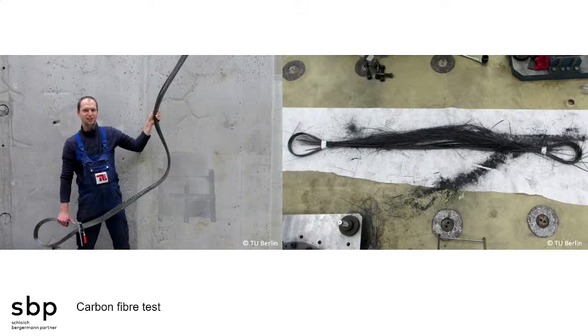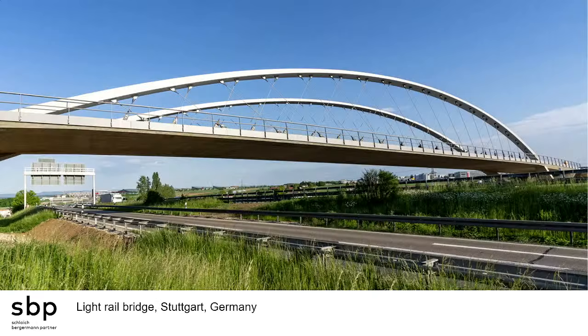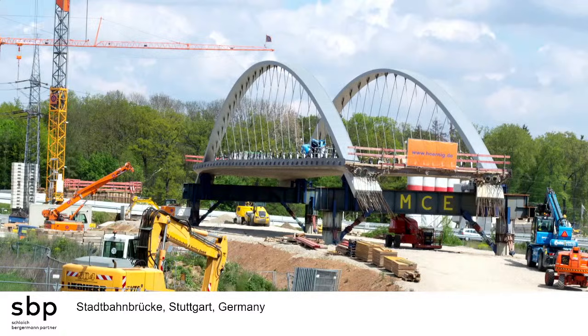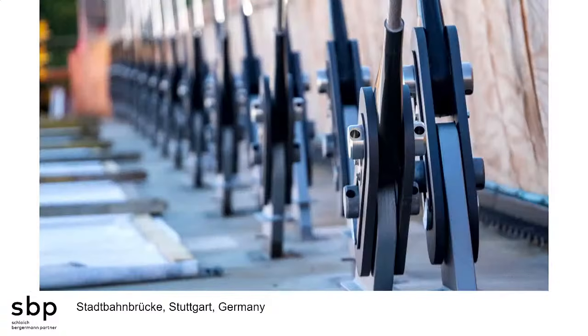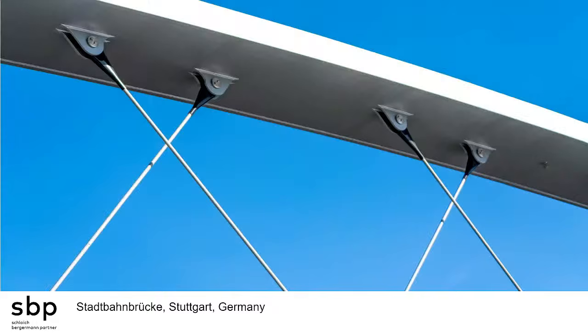I just tell you, don't break them. Make sure that this brittle material doesn't break, because you end up with a lot of fibers and a lot of powder, black powder, after a big bang. But this research has led to bridges like that. This is a network arch bridge where you get a lot of stress changes due to live load, and if you would make the hangers in steel, they would have big diameters because of fatigue design, while with carbon fiber you can end up with very slender hangers, as you can see here. The entire bridge was prefabricated. This is the carbon fiber anchorages, and here you can see how slender these hangers are in carbon fiber.